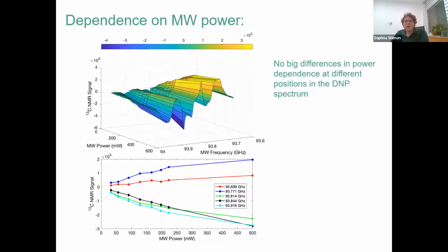So we did some experiments to check the different experimental parameters that we can change. The first thing we checked was the dependence of the enhancement on the microwave power. Almost all the experiments that I showed were at about 200 milliwatt, but we were able to get also one data point at 500 milliwatt with a larger amplifier. So you can see that at these powers where we're working, we're power limited.